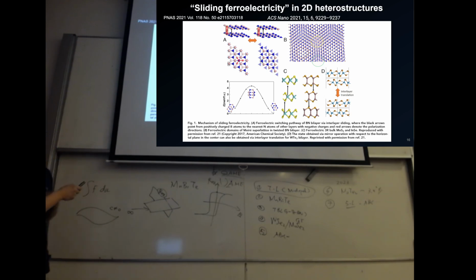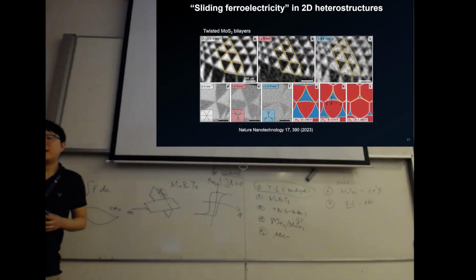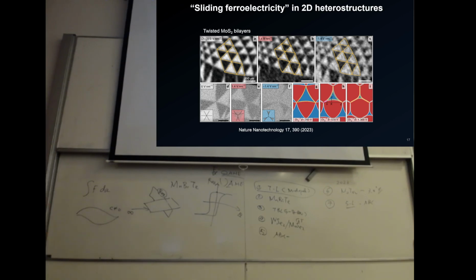Depending on the sliding distance or the displacement between the top and bottom layers, you will have different polarization potentials for the layer. At the end, it will be a very prominent effect even in the 3R structure, which is the rhombohedral. So they claim that this is a general behavior which is universal. You should have this sliding ferroelectricity as long as you have this 2D moire structure or the 2D rhombohedral structures, which has been shown to be true, but actually the polarization field is very low. For application-wise, I would say so far I couldn't find any real application potential for that. But at least for fundamental physics or fundamental research, it's very interesting.